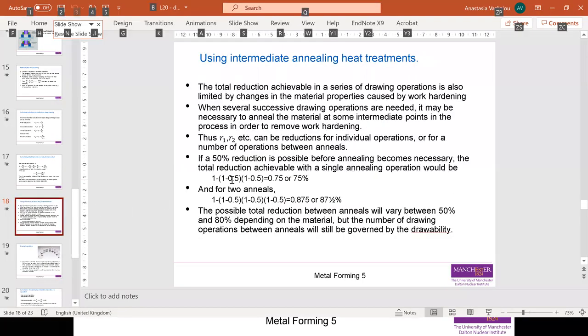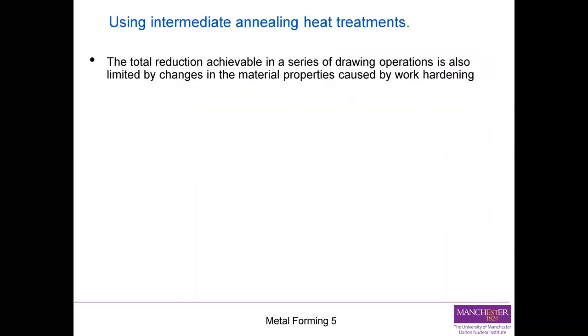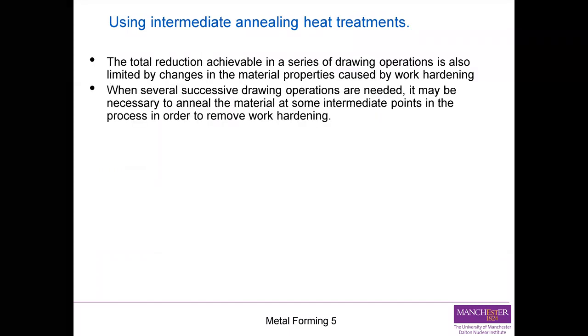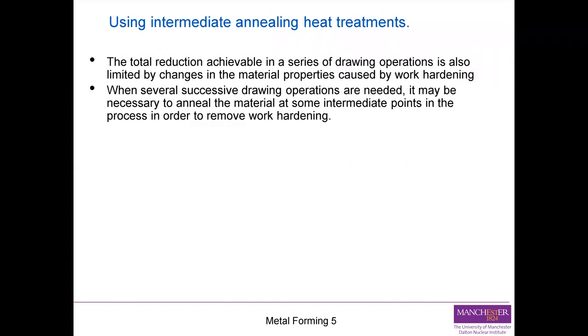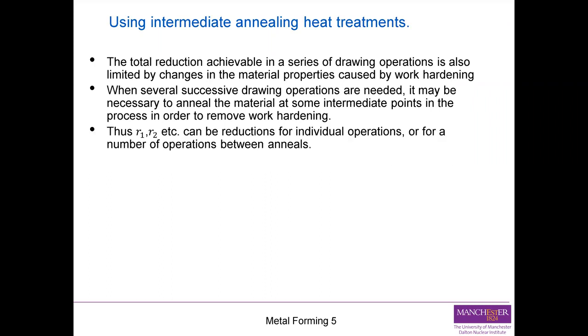So let's move on to the next slide, which refers to the use of intermediate annealing heat treatments. The total reduction achievable in a series of drawing operations is also limited by changes in the material properties caused by work hardening. When several successive drawing operations are needed, it may be necessary to anneal the material at some intermediate points in the process in order to remove work hardening.